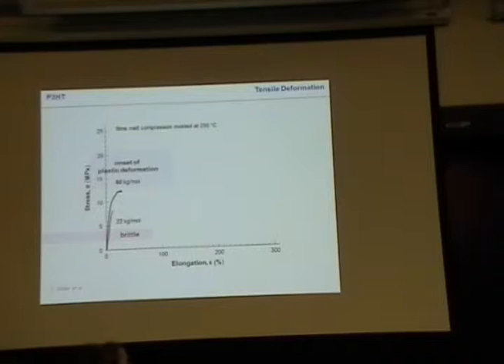How do we know that we have three entanglements per chain at this specific molecular weight? If you see that we have a deviation from linear behavior — the linear regime is called Hooke's law — when you stretch this material further, you have this deviation, called onset of plastic deformation. Meaning if you stretch the material, it doesn't break; it will stay in this deformed state. Because it's just a tiny bit, you know this is the onset — that's where we have three entanglements per chain.